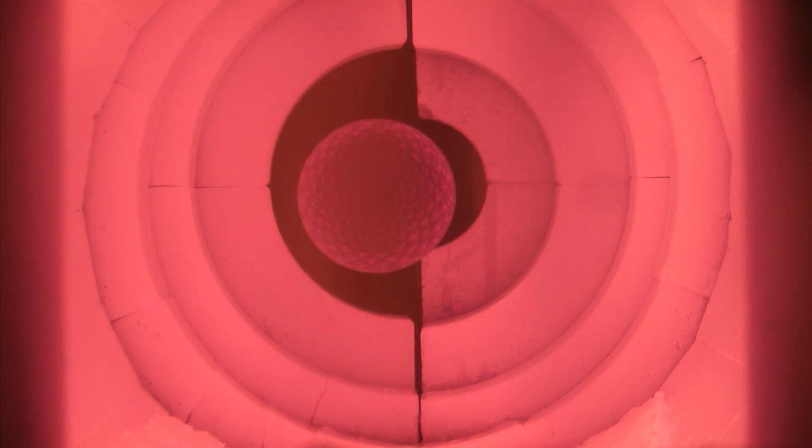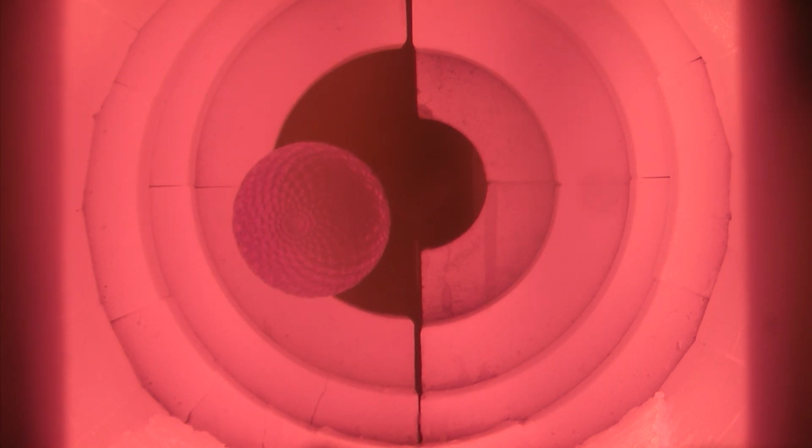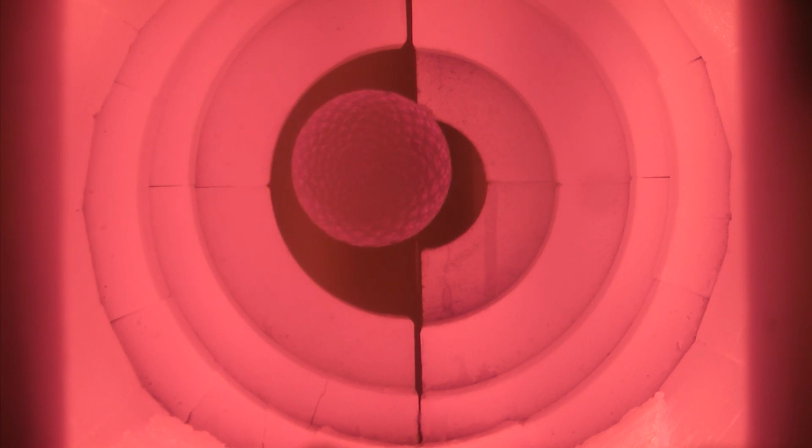Now, this particular bowl form that he's going for is a fairly low bowl. And those can be really challenging forms to make. Of course, Chris is really good at it, so it's going to look really simple, but he's got a nice round bubble right now. He's focusing heat mostly on the bottom 3/4 of that bubble. And when he comes out, he'll hold it slightly up into the air. That'll allow the glass to backset on itself, kind of gravity compressing that bubble.